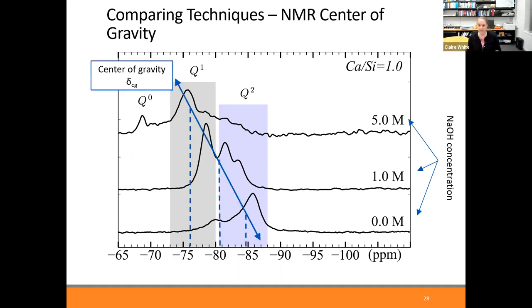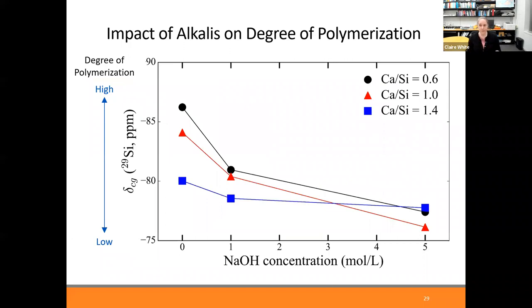So we can actually quantify this change in silica connectivity by calculating the center of gravity for each of these spectra. And then I'm going to plot the center of gravity for a whole lot of samples on the next slide. This is what's shown here. On the x-axis, the gels were synthesized using various concentrations of sodium hydroxide. We actually synthesized gels with varying ratios of calcium to silicon, and we're plotting the center of gravity from the NMR results versus sodium hydroxide concentration that was used for synthesis.